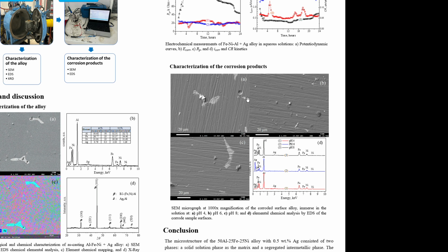It is suggested that future investigations study the corrosion mechanisms using other electrochemical techniques for this alloy in both acidic and alkaline media. In summary, the low corrosion rate values observed in all 3 conditions were associated with the passive corrosion products layer, primarily composed of aluminum hydroxide.